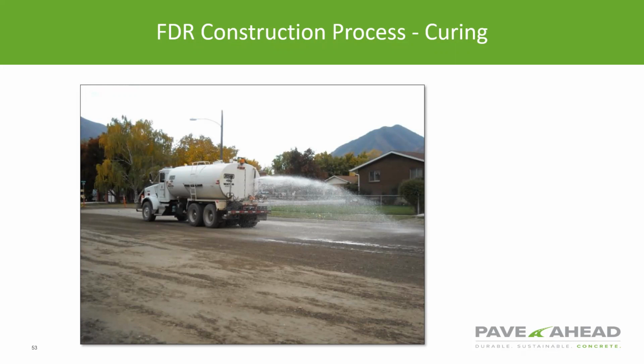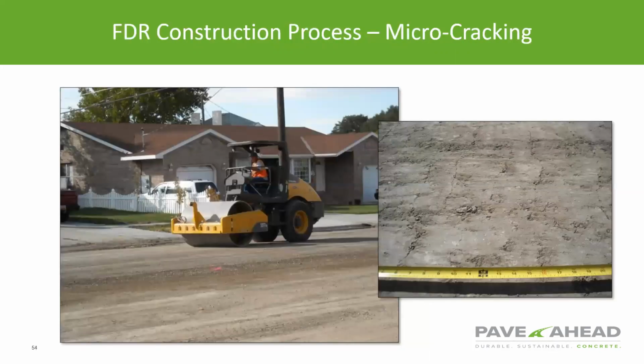If you can keep it damp, like, we've had some projects where we treated it and we had some issues with frost maybe coming in, and we put the gravel back on top. We actually wet it down when the gravel was sitting right there, and we just laterally moved it over, kept people off of it with loads, and let that gravel become the actual membrane that trapped the moisture in, and thus allowed it to slow cure too. So it just depends on the cost you want to spend.